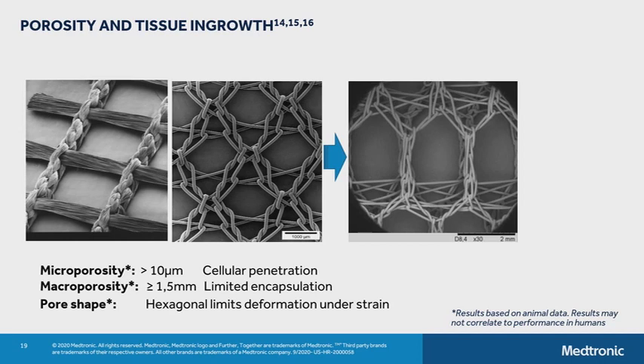We create textiles that have macropores that are greater than 1.5 millimeters in size. Additionally, warp knitting allows us to control the shape of the pore, and this is an influencer on the material response as well. Hexagonal pore shape has been shown to be more stable and not susceptible to deformation under strains. This is important because if we were to take a textile and pull it in one direction, we don't want the pores in that direction to collapse and shrink the size of the pore.